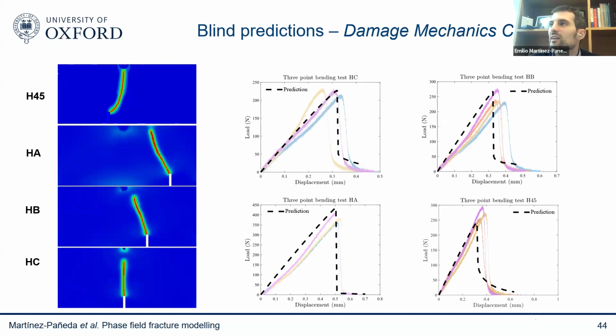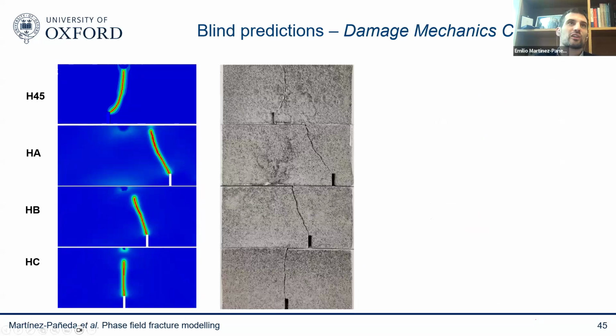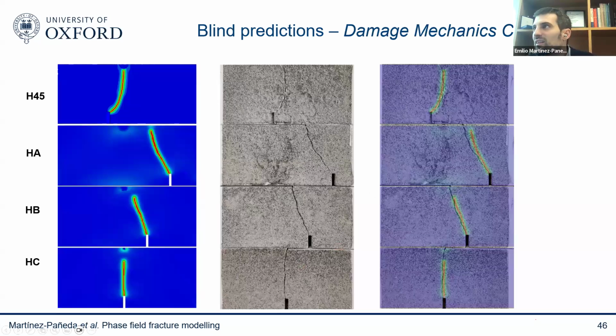First, in terms of force displacement, they did 3 replicate experiments, and you can see we got a very good agreement all across the board. There are little differences here and there, but more or less they are within the experimental scatter. So we were quite happy with the outcome. Again, this is a blind prediction. We did not see anything of the experiments. Then they also released the crack trajectories. And again, as you can see, the experimental crack trajectories are very well aligned with ours. In fact, we can superimpose them, and you can see the agreement is almost perfect. So we were quite happy. I mean, it's not that difficult to get these things when you are allowed to recalibrate your model. But if you do it blindly, this is quite nice, I think.